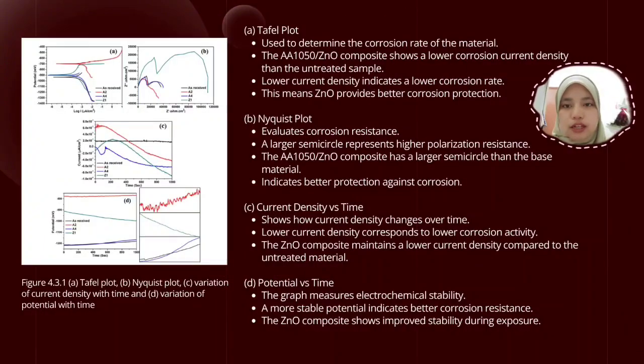So for this slide, it evaluates the effectiveness of the zinc oxide corrosion inhibitor using several electrochemical tests. From this graph, first, the Tafel plot shows that the zinc oxide composite has a lower corrosion current density compared to the untreated material. This indicates a lower corrosion rate. Second, the Nyquist plot shows a larger semicircle for the zinc oxide composite. A larger semicircle represents higher polarization resistance, which means better corrosion protection.